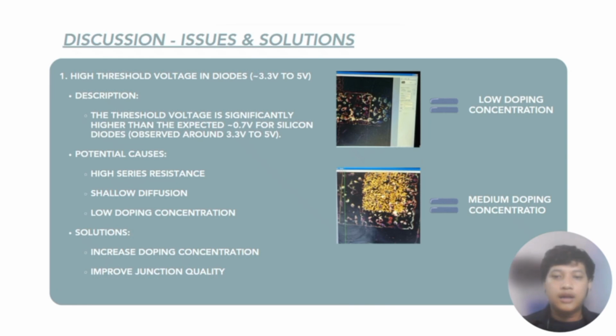Based on the IV characteristics graph from the previous session, we had a discussion about the issues and came up with a few solutions. For the first issue, the high threshold voltage in the diode: typically, the ideal diode will give us a 0.7 volt threshold voltage, but from the graph we get a value of about 3.36 volts up to 5 volts. The problem, as you can see from the image, is that the low doping concentration and medium doping concentration cause this issue. So the solution is we need to increase the concentration or improve the junction quality.